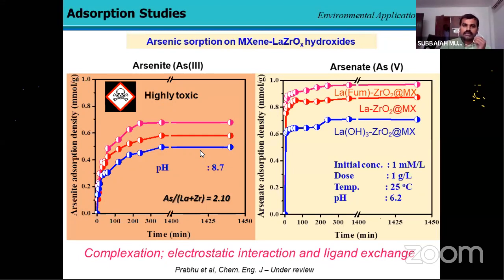capacity for the arsenate phase, due to the pH of the solution, where for arsenate the pH is 6.2 and the arsenic is in the +5 oxidation state, whereas the oxidation state of arsenite is +3 at pH 8.7. Hence arsenite is more highly toxic than the arsenate species. Then we found that the arsenic to metal ratio was 2, so we confirmed that each metal can adsorb 2 arsenic ions.